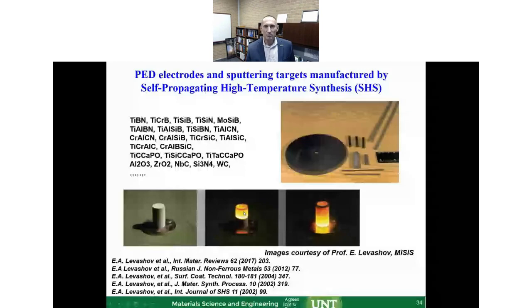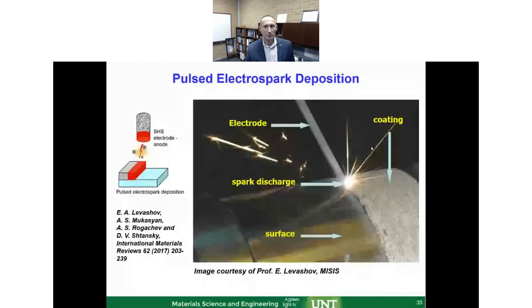Every year they develop multiples of these. And as part of this technique, a self-propagating synthesis shown here, you can combine very high temperature materials together into dense electrodes, and you can then use them for making coatings. One of the techniques which can be used, for example, is electrospark deposition, to be more exact, pulsed electrospark deposition.